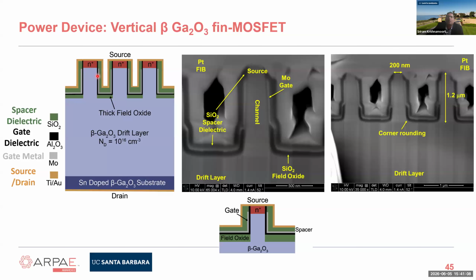So we define narrow channels, about 200 nanometer wide channels of low-doped gallium oxide. And then we use a metal oxide semiconductor junction on the sidewall of this fin for the gating purpose. And so that way you gate from both sidewalls, and then you control the current flow from the source to the bottom drain, right? So it's a vertical FinFET, no junctions, no p-type layers involved, all unipolar. So hopefully these can be fast switching